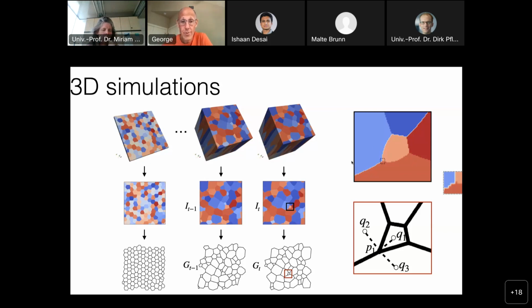And how can we construct the graph? Essentially, we're going to have this junction between grains, and the edges will indicate the connectivity between two junctions. Notice that here there's some curvature. We're going to ignore this, and we're not going to model it in the reduced model. To find the junctions, we look at points in the phase field solution in which the neighbors have three different phase field values. This is a junction between grains, and this junction in the phase field becomes a